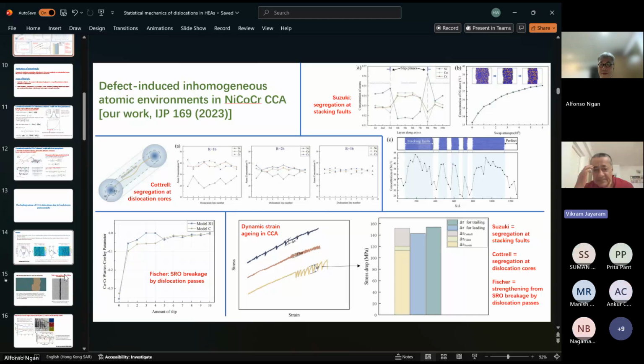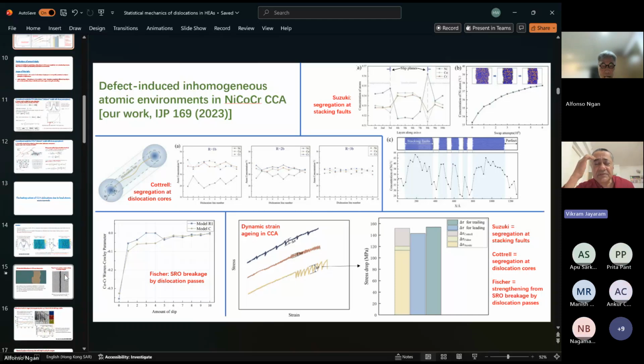Yeah. I just wanted to clarify this point about stacking fault energy, which has been brought up in the context of BCC alloys and so on. My understanding is that the magnitude of the width of the stacking fault is not relevant here. Am I right? No, it's not relevant. As we calculate these contributions, the width of the stacking fault doesn't matter because the resistance is independent of the width. Okay. But this is FCC.